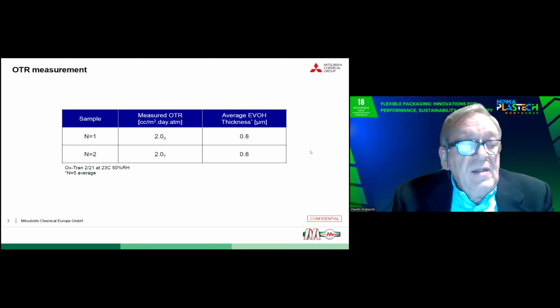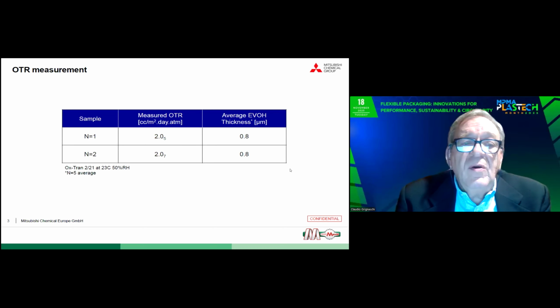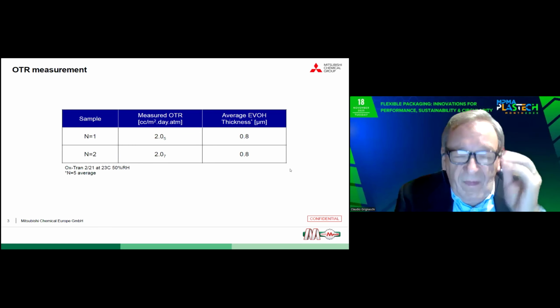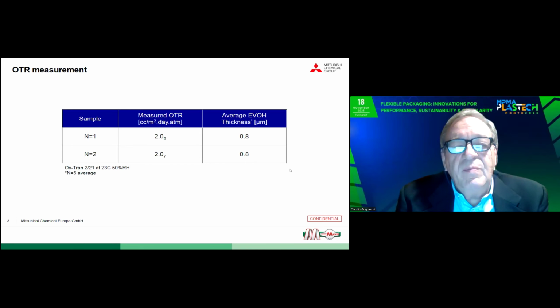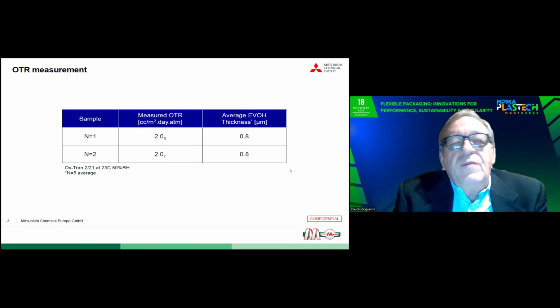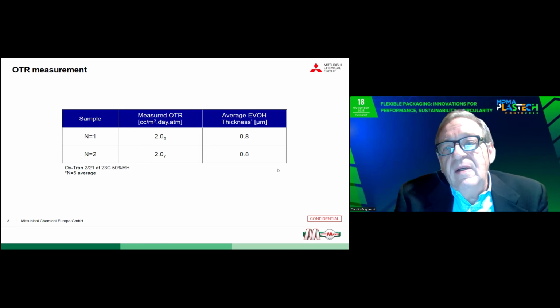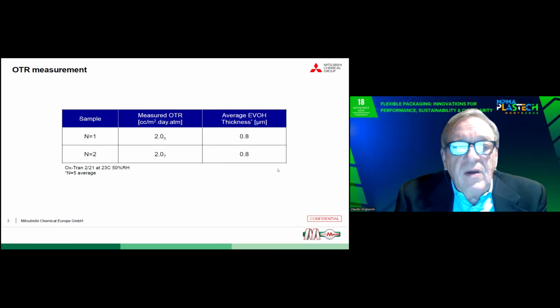This means that with a line like this, you're able to offer, if you use machine direction oriented polyethylene, a laminated monomaterial film with the outer layer MDOPE printed inside—offering a real alternative to today's structures laminated with PET, BOPET, or BOPP.